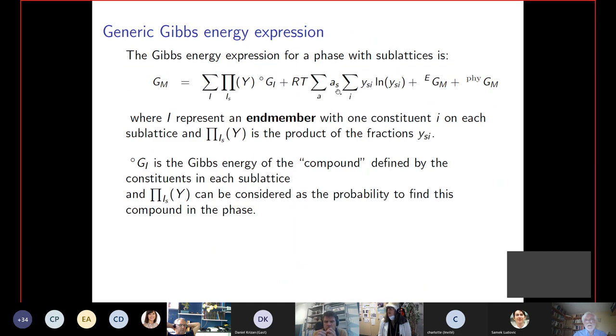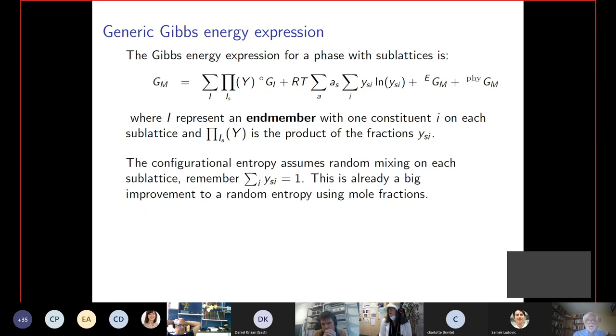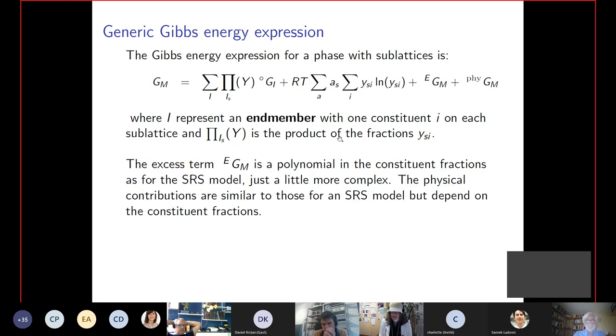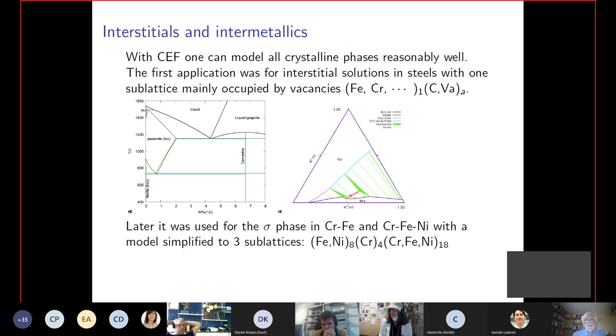And the modeling is basically setting up a function like this. You have a Gibbs energy for the phase, and then you have these, which are basically the lattice stabilities, how stable the pure element is, where you have different kinds of ordering on the different sublattices. This is your configurational entropy, which depends. CALPHAD normally uses a random mixing on each sublattice, but having sublattices, you have a weight factor depending on the number of sites. Each sublattice basically has fractions that sum up to unity. And then you have an excess term, which depends on the bonding of the types of elements. And then you have a physical contribution like the magnetic.